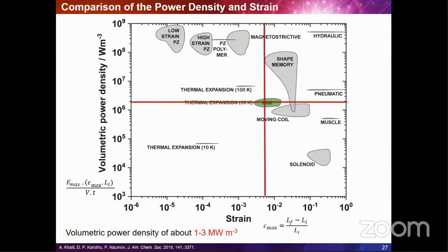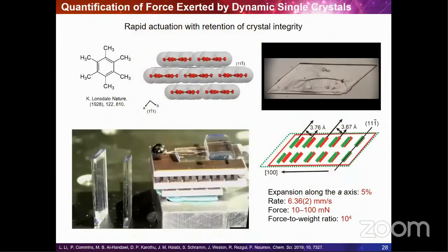This is another example that I would like to show, a very simple compound, which is hexamethylbenzene, a very old compound whose crystal structure was determined back in 1928 by Kathleen Lonsdale. And this is an interesting compound because it also undergoes a very fast phase transition. It is capable of rapid and complete structure switching, and it undergoes a martensitic phase transition. This transition has tremendous potential as a thermally driven organic actuator.